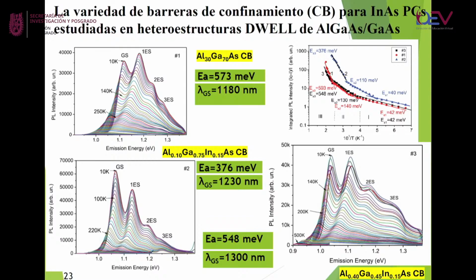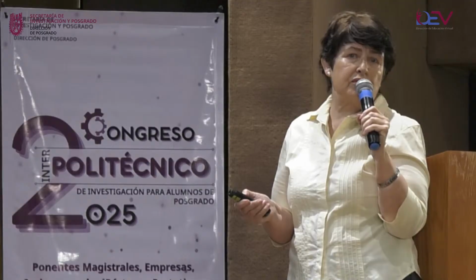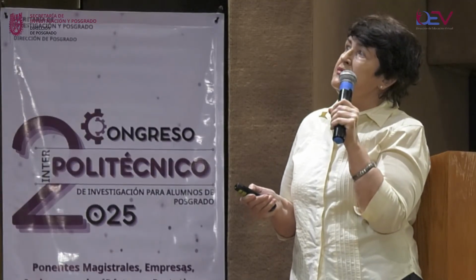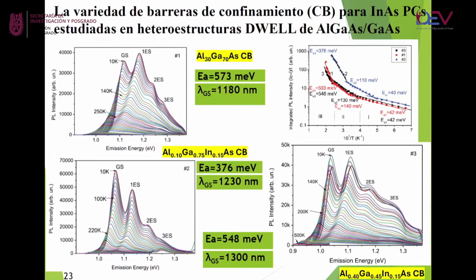Then we used another confinement barrier. The result was also not very nice. And only when you use another composition of alloys in the confinement barrier with a higher percentage of aluminium, we receive emission, as you could see, corresponding to the transmission windows of optical fiber, together with a higher confinement barrier near the quantum dots.